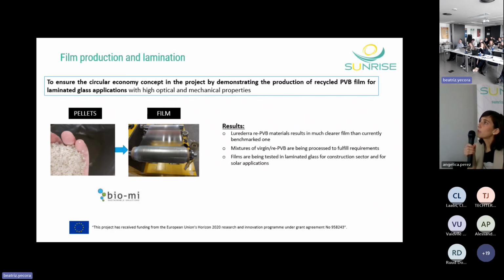Then the project is also working to produce with these recycled PVB flakes, these stabilized pellets, and then with these stabilized pellets go to a film product again and check if this is of enough quality. We anticipated in the previous workshop that we could need a mix with virgin PVB. Because we saw in the first test that when we use this mechanical chemical recycled PVB from the treatment in Luredera, the results were a much clearer film than currently recycled material in the market, but still needed to improve the optical quality.